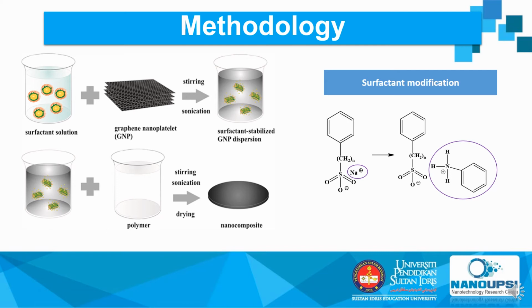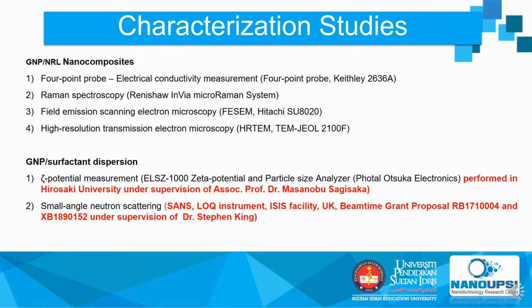which is summarized in the following figure, where at the first stage the surfactant solution is mixed with, in this project, graphene nanoplatelets through stirring and sonication to produce a surfactant-stabilized GNP dispersion. Meanwhile, the surfactant-stabilized GNP dispersion was added to the polymer, followed by sonication and drying to produce the nanocomposite. For the nanocomposite, four different techniques were used to characterize it, including four-point probe to measure the conductivity, Raman spectroscopy, FESEM, and HRTEM. Meanwhile, for the GNP surfactant dispersion, we used zeta potential as well as small angle neutron scattering.